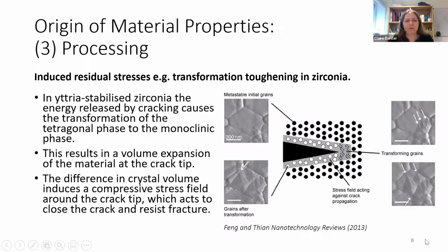And what was happening was the energy released by the cracking causes a transformation of the tetragonal phase to the monoclinic phase. And they're not that different, these crystal structures, but they're different enough that you see a significant volume expansion at the crack tip. And that difference in crystal volume gives rise to a compressive stress around that crack tip, and that acts to push the crack back together.